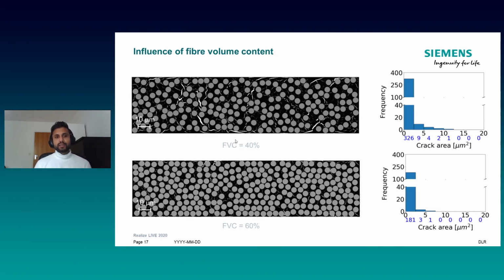And the reason behind that is, since I increased my fiber volume content, the matrix volume content decreased. And there is no space for cracks to come together and grow into a larger crack. And this leads to the conclusion that I need not try another combination, or maybe even the same combination but different fiber volume content, to see where I end up. I can do it virtually. I can test which fiber volume content is optimum for this carbon-carbon block formation, and then go into the manufacturing process and try it out.